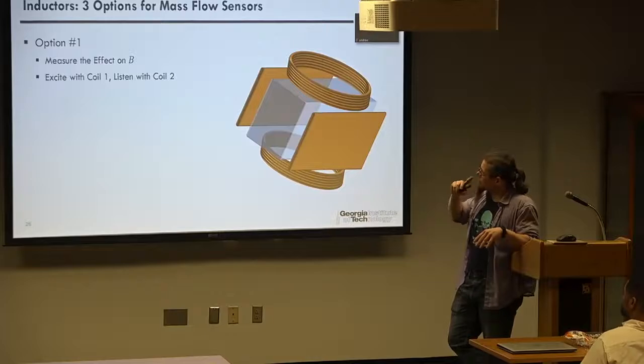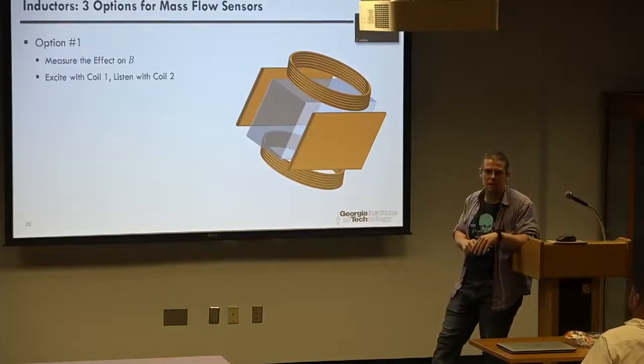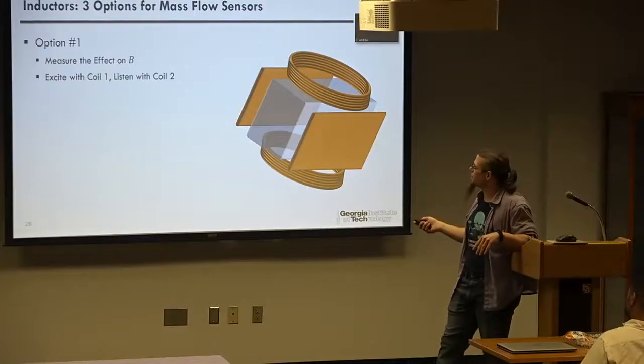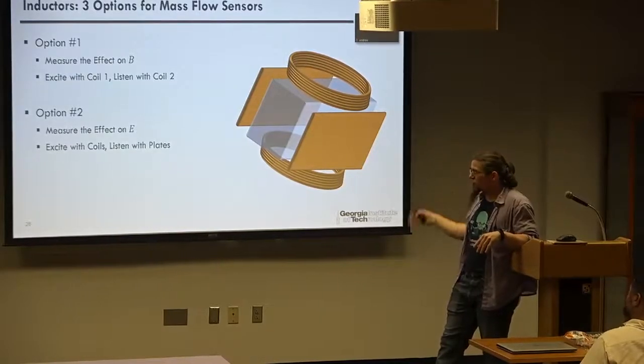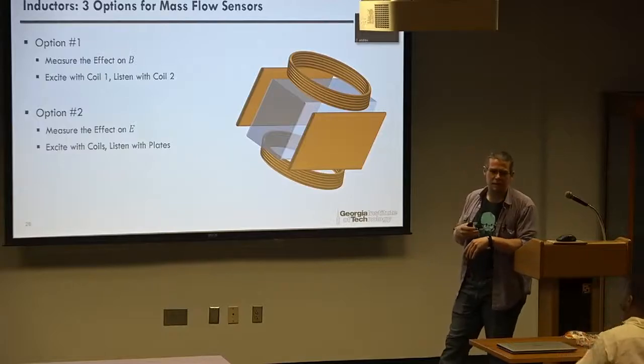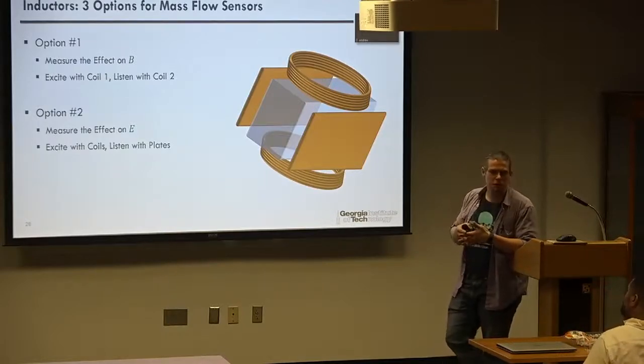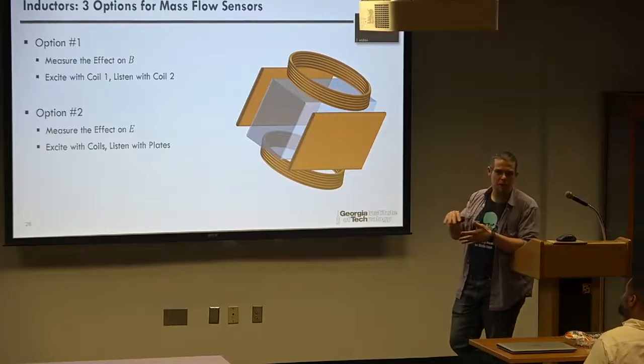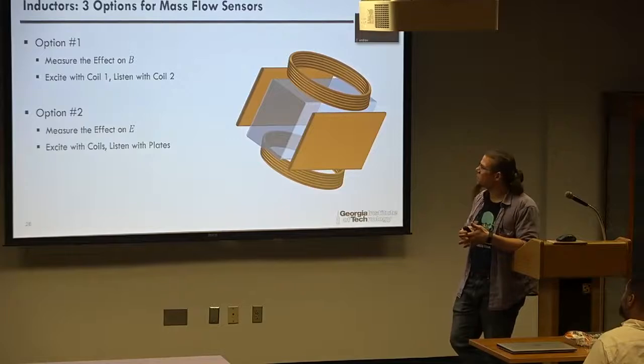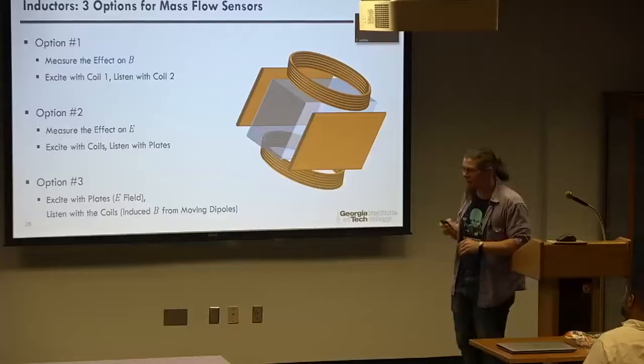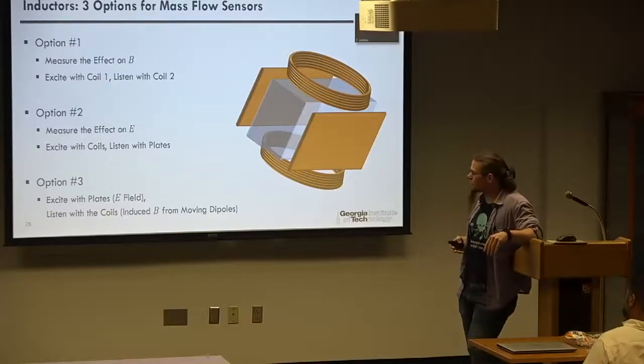The first option is to measure the effect on the magnetic field. For this, we're going to excite one coil and listen with the coil on the other side of the flow to see how that magnetic field is being changed by eddy currents generated in the powder. The second option is to activate both coils and listen with the plates. So that's the coupling between your electric field and your magnetic field. An oscillating magnetic field is going to stand up an oscillating electric field. Powder flow is going to interrupt the oscillating magnetic field, so it'll interrupt the oscillating electric field. We may be more sensitive with that, or we may not. We'll find out when we actually test it. Option 3 is to excite the plates, generating a standing electric field.